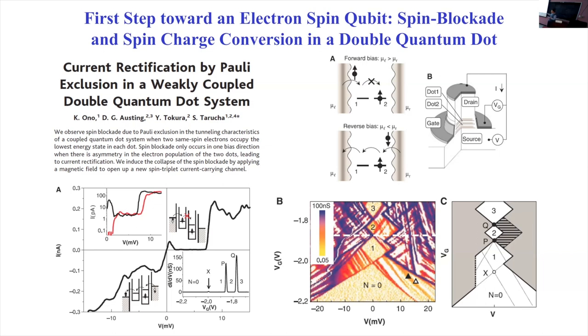Okay. So this Pauli blockade basically takes advantage of that discrepancy between the spectrum of singlet versus triplet, so that if the electron is in a singlet, you can tunnel through. If it is a triplet, it doesn't, because the transport is blocked, and that gives you this current rectification phenomenon. But the key observation there really is, at the end of the day, the correlation between the spin state and the charge distribution. Right, because for singlet and triplet, one of them can go into the 0-2 configuration where two electrons are in one dot. Well, for triplet, in some particular bias regime, it can only stay in the 1-1.